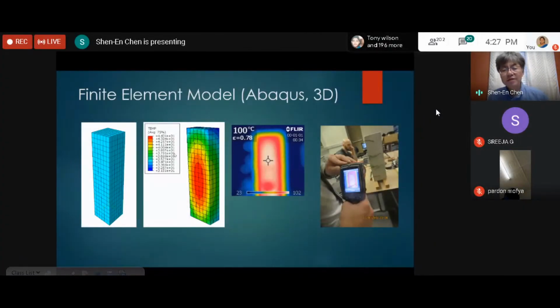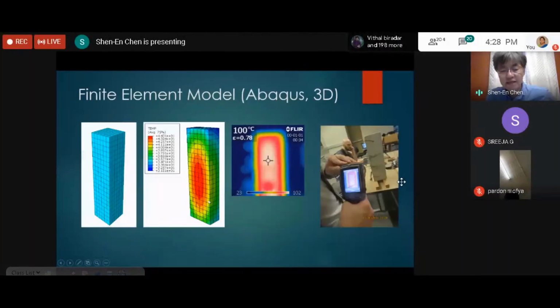This is a finite element simulation. To understand what is physically happening to those free cool down elements, we developed this finite element model to show the temperature change through the cooling process. And as you can see, the finite element model is consistent with what we measure using a thermal infrared camera. The infrared camera is measuring the surface change of this element, but the finite element results that we're showing are actually the inside of the element.